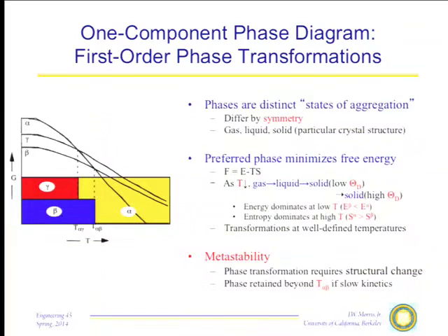So what would our phase diagram look like then? At low temperature, our preferred phase would be gamma, because it's preferred to alpha, and beta is an impossible phase, kinetically. As we come up in temperature, alpha would cut through the gamma curve here. So our phase in that case would be gamma up to this temperature, T alpha gamma, and then alpha at higher temperatures. And so we can have these metastable phases introduced if we suppress the formation of the other phases.